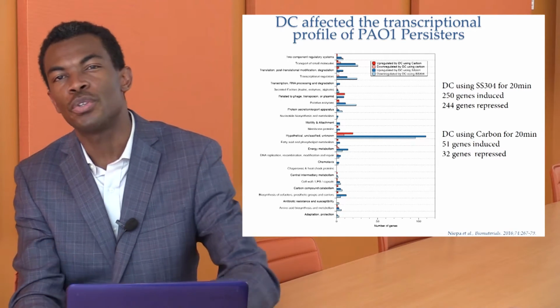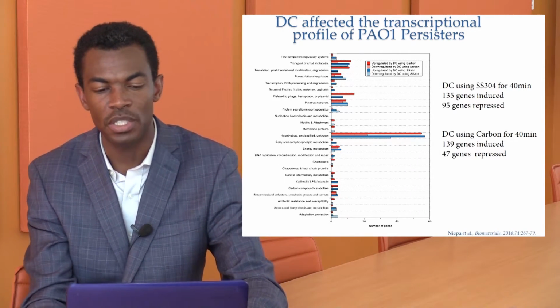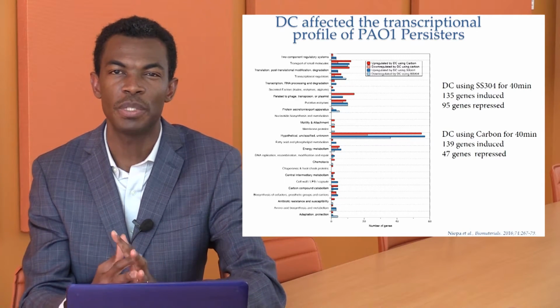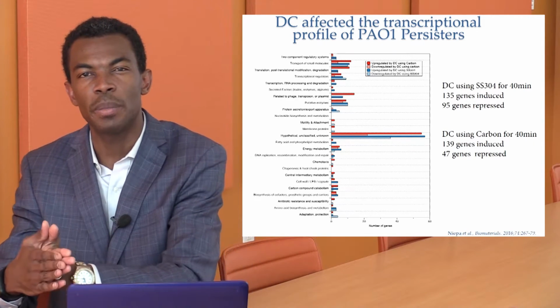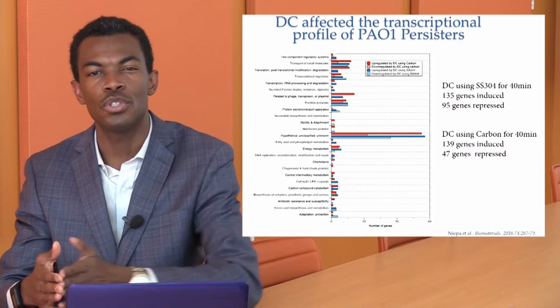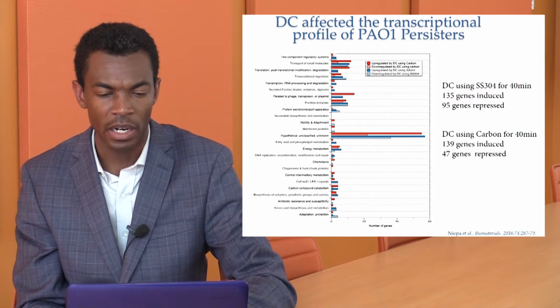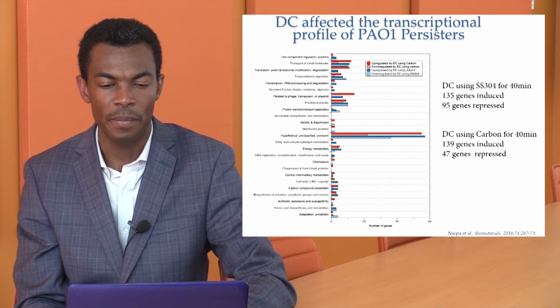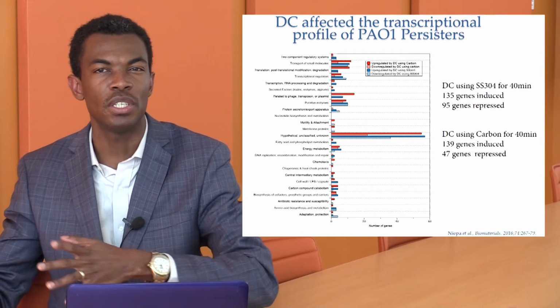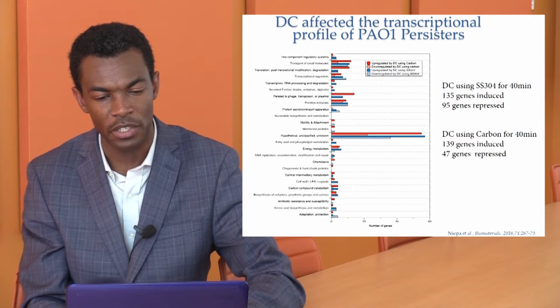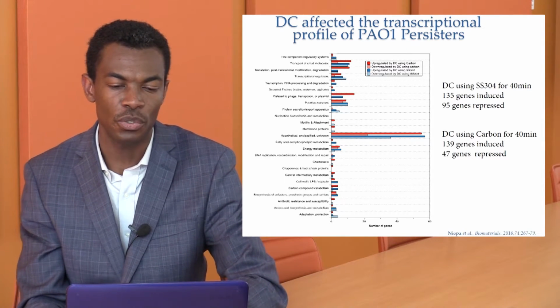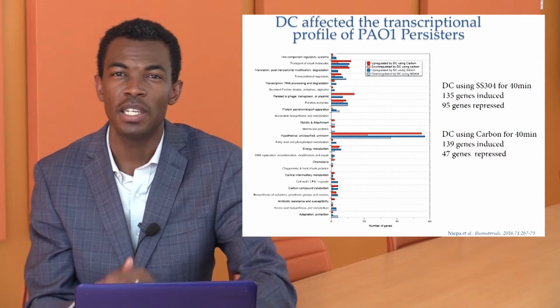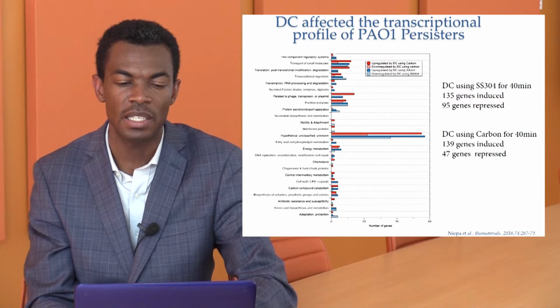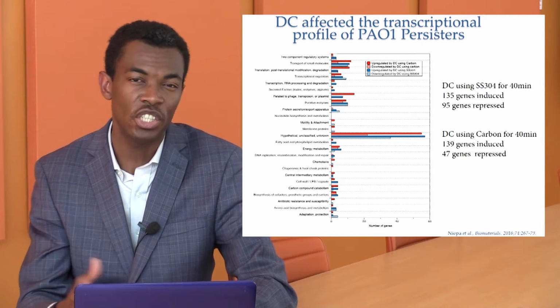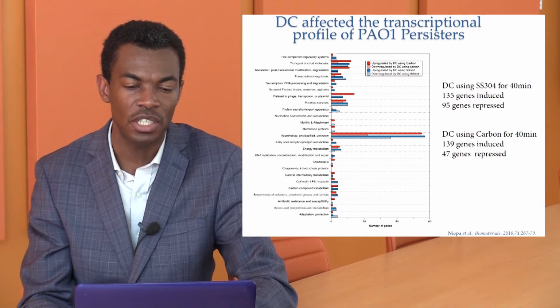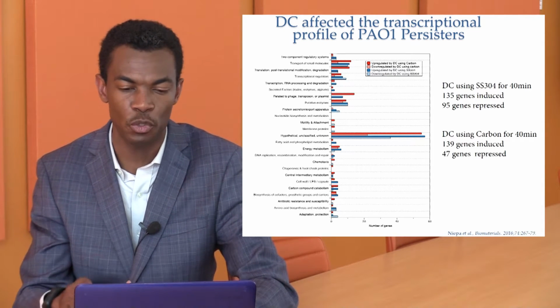When we go further to perform a treatment for 40 minutes, then the picture becomes something else. We know that a longer treatment mostly affects the cells, just as we saw in our biofilm treatment, where the 2 hours were more efficient compared to the 1 hour treatment. Here, we compare the 40-minute to the 20-minute treatment, and using stainless steel electrode, we can realize that, again, many genes are involved, 135 genes versus 95 that are claimed to be repressed.